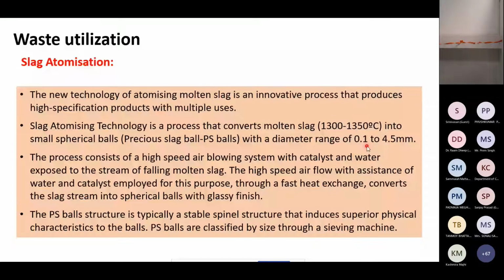The process consists of a high-speed air blowing system with catalyst and water exposed to the stream of falling molten slag. So whatever slag is generated is to be molten at a high temperature, around 1300 to 1350 degrees centigrade, and exposed to the stream of catalyst and water. With this, in the presence of catalyst, water, and high temperature, the molten slag produces these small spherical balls. That is called precious slag balls.